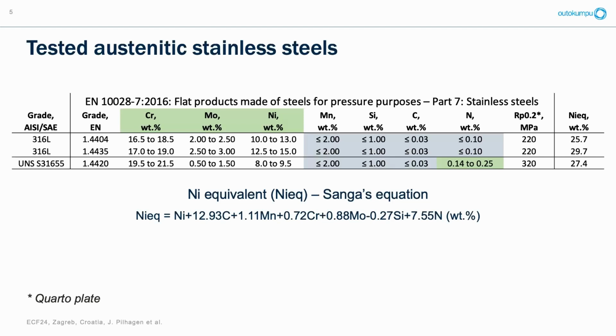And the reason why we're interested in nickel, or what is called nickel equivalent, is that it seems from the literature that the hydrogen embrittlement, at least in the SSRT condition, is due to this susceptibility for strain-induced martensite. And if you look in the different standards and norms, they typically specify a nickel content of 12.5 or 13 weight percent for hydrogen gas applications. So the austenite stability is an important thing to consider. This nickel equivalent is a way to also include the other elements in this stability.